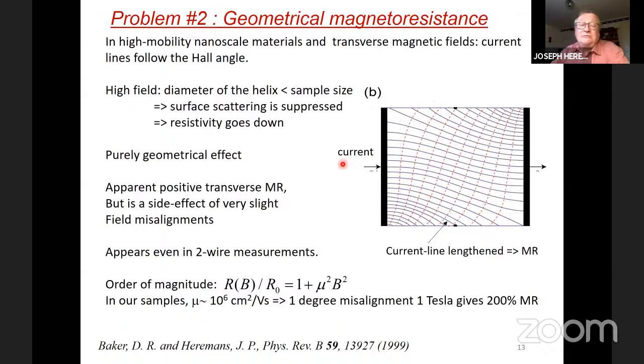Another problem, which we are going to run into at length, and I will come back to this and probably spend 10 minutes on it, close to the part of my talk where I verified the Wiedemann-Franz law, is the geometrical magnetoresistance. So in contrast to the previous drawing, where we had the field parallel to the current, we are going to consider the case where we have the field perpendicular to the plane of the view graph here, perpendicular to the current. Not, of course, that we do this on purpose, but samples, when they get mounted, are always mounted with a very tiny misalignment, which is a critical parameter in our problem. Well, if that is the case, then the Lorentz force distorts the current lines a little bit like shown here, which, as you can see, lengthens the current lines and creates a positive magnetoresistance, a parasitic geometrical positive magnetoresistance.